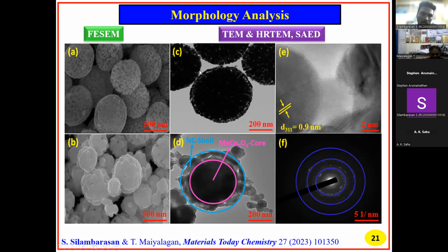surface. Then after that, figure C is the pure MnCo2O4 for TEM analysis. Once more, we confirm the uniform porous structure. Then figure D confirms the core-shell structure, with the inner layer of MnCo2O4 and the outer shell of nitrogen-doped carbon. Then figure E is the calculation of the d-spacing, about 0.9 nanometer. The plane is 311. Figure F is the SAED pattern.